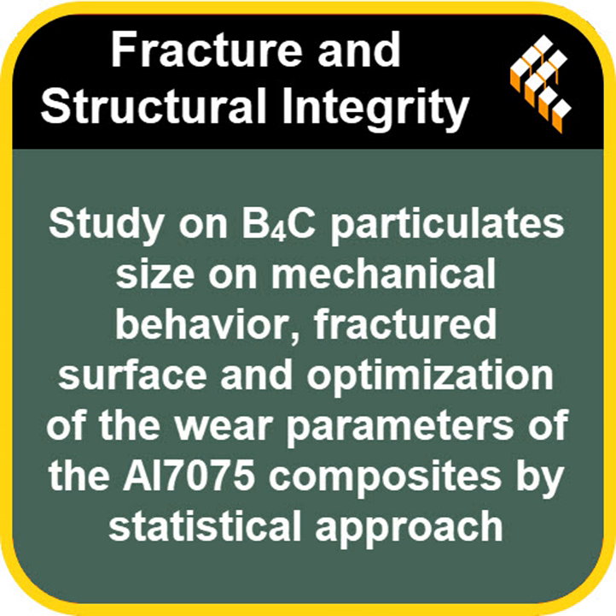And tensile strength. How much pulling force can it withstand before it breaks? Again, an overall improvement. The MMC showed about a 13% increase in tensile strength compared to the base alloy. And here, too, the nano B4C particles really shone. They significantly enhanced both tensile strength and wear resistance. Why was nano better for tensile strength? It seems to be down to a couple of things. More efficient load transfer within that metal matrix, like we saw with hardness. Also, a reduction in stress concentration points.